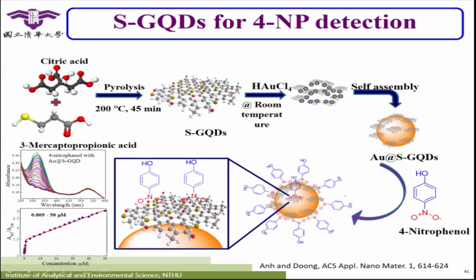We use citric acid and some sulfur salts, mercaptopropionic acid, and then put the gold precursor inside. Since the GQD is the reducing agent, it can reduce the gold ions into gold nanoparticles, so we get the gold GQD. Then we can use this to decompose nitrophenol as well as to detect nitrophenol. Their efficiency is also quite good. We published this 2 years ago.